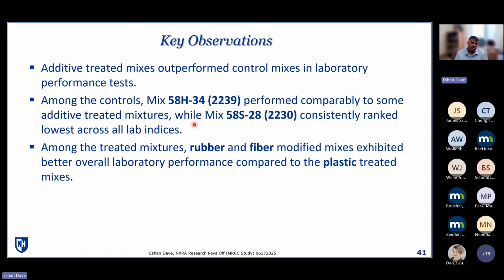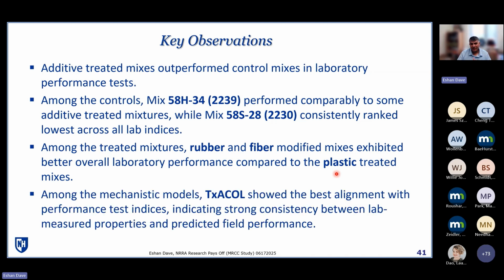Within the treated mixtures in general, the rubber and fiber modified ones exhibited better performance than those treated with plastic, but you have to take that with a grain of salt, because that depends. We had two types of plastic products, and the dry plastic was the one that consistently underperformed compared to most of the other products.